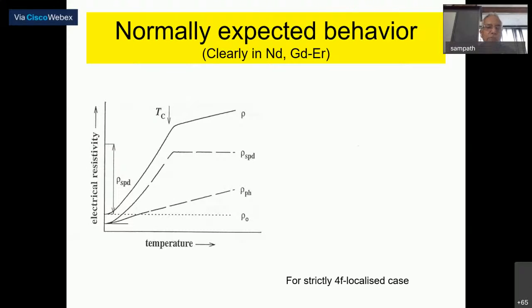Okay, now let me come back to the electrical transport, which is going to be the main data which I'm going to emphasize. If we take a normal rare earth material, and when I say normal, as I already said, where we don't have 4f electron delocalization effects, a simple material like gadolinium, you have 3 contributions basically for electrical transport.